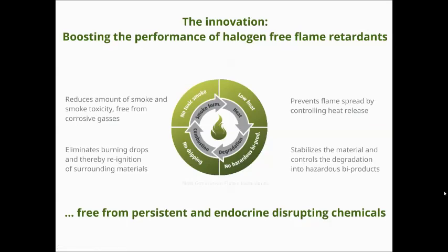But as far as the benefits from the fire safety, we see that these functional polymers actually propagate cross-linking in the backbone of the materials that we work with. And again, those are polyolefins that it's compatible with. It prevents the flame spread and controls and reduces the peak heat release rate of the materials. So that means it burns slower. You control the burning process. We also see that it starts burning a bit later. We stabilize the material to some degree, so you get an increased degradation temperature.